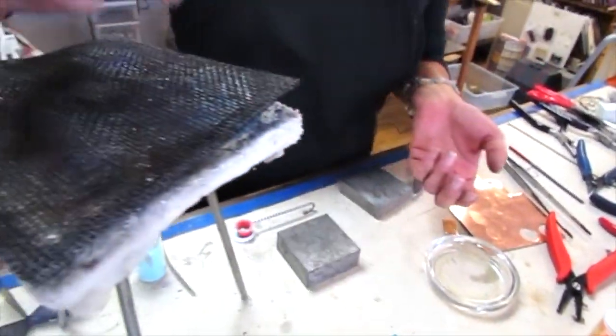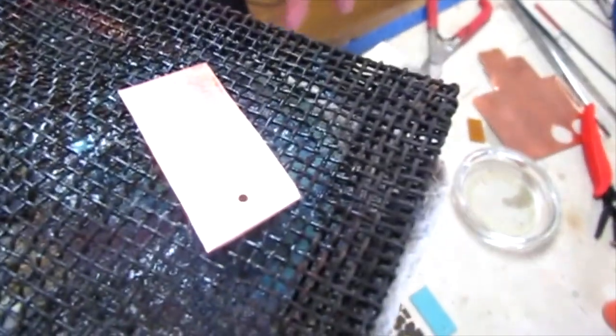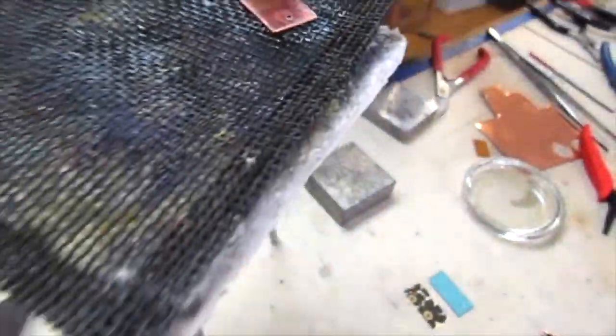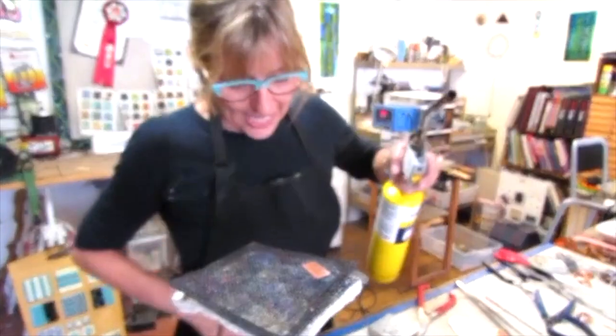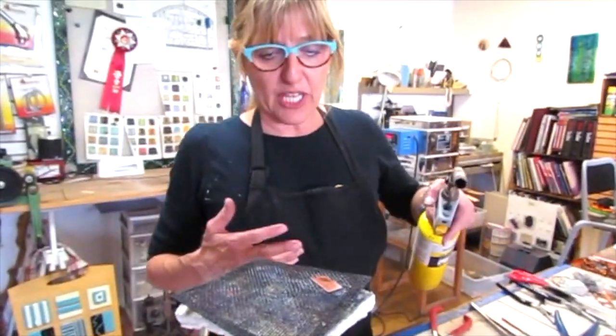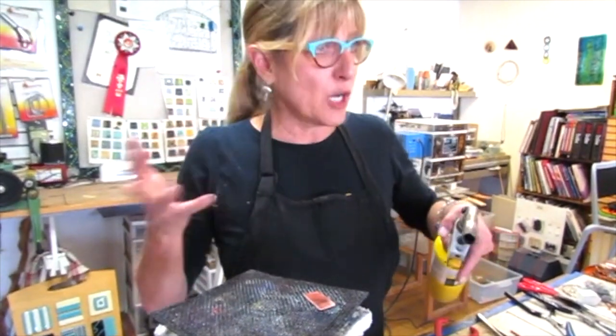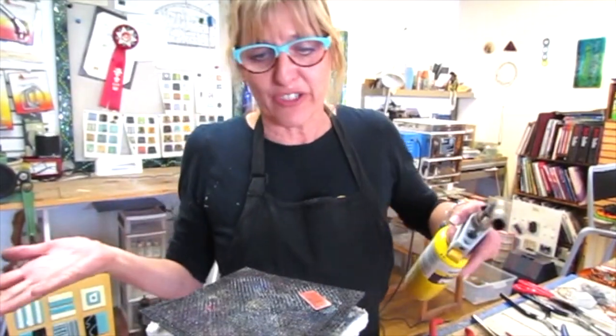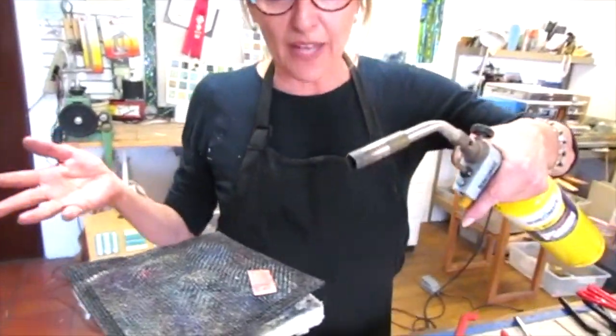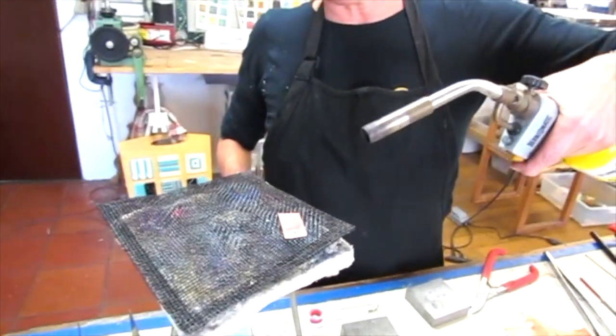I'm going to put this up on my tripod. To prep the copper I use fire — you want your copper as clean as possible, so I burn off everything. Also, this initial layer of enamel can peel up; glass likes a hot surface to stick to. I've got my MAP gas and my push-button torch.